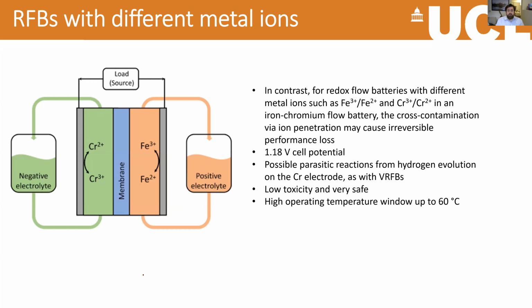We can also use different ions, as I say, there's a whole host of different types of ions that you can use, and the iron chromium cell is actually quite a well-developed one. This has a similar sort of cell potential as the all vanadium case, because you're using different species in the two electrodes here, and so crossover can be an issue. If some chromium goes over to the iron side, for example, then that reduces the useful capacity that you have in your negative side. But the benefits here are low toxicity, it's quite safe, and you've actually got a higher operating temperature than you do in the vanadium battery, because as you go to higher temperatures in vanadium, you start to reduce the solubility of the vanadium species in the electrolyte.